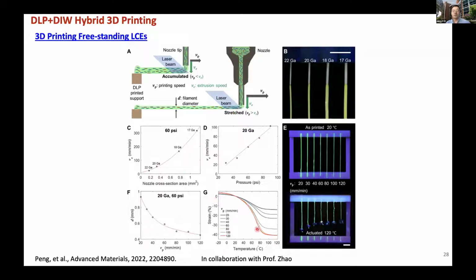You can see here that as you move too fast, most of your mesogens are already aligned, then you gradually lose the gain that you have. But roughly we can achieve about 50% shrinkage, which is pretty close to what most people obtain by just printing on the substrate. Typically, people achieve about 50%. So we're pretty good in terms of the actuation we can achieve.